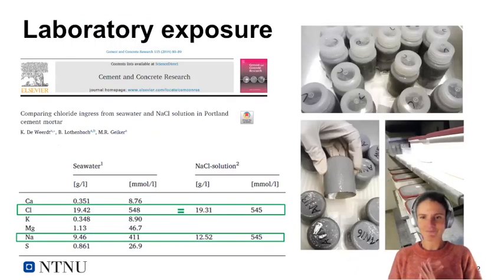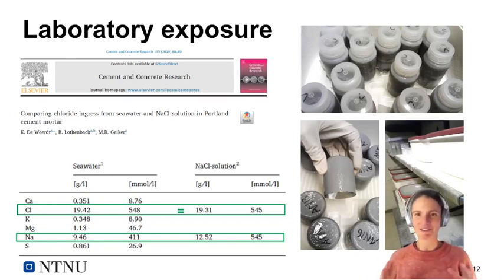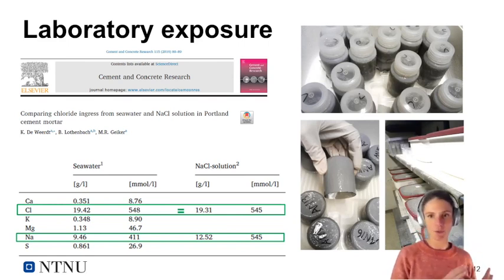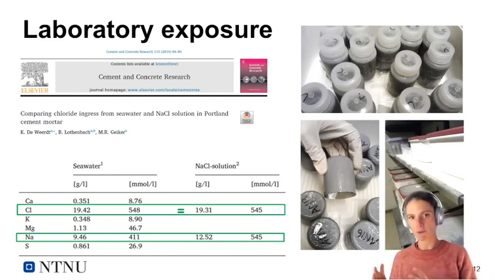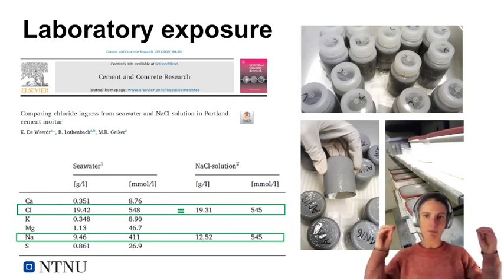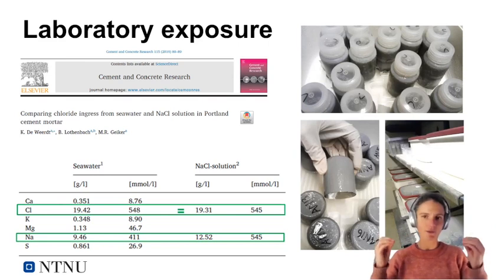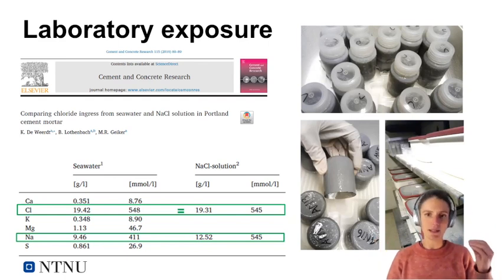So, as I normally do, if something doesn't really make sense, I try to simplify it and make a small experimental setup in the laboratory. Though this was not a small setup. I made a bunch of different mortar samples here, and I compared chloride ingress from seawater with chloride ingress from sodium chloride solution with a similar chloride concentration. So I have the same potential in my solution, the same chloride concentration, but in one it's just pure sodium chloride solution, and in the other one it's seawater.